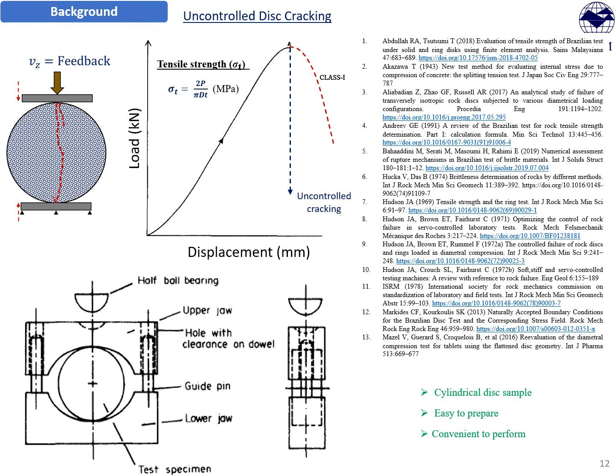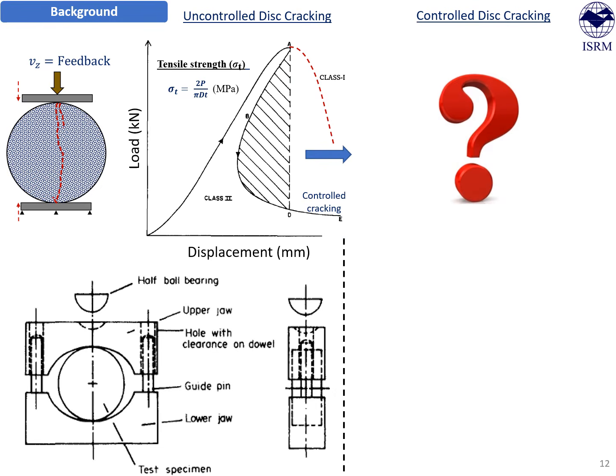We can see that this experiment can efficiently capture the class 1 behavior of rock. However, it cannot capture the class 2 behavior, which is more common in hard and brittle rocks. In those cases, as we reach the peak load P, the specimen cracks uncontrollably and the load drops immediately to its residual strength. And there was no way it could capture the class 2 behavior, which indicates the true mechanical post-peak behavior of the given rock type or the brittle material.